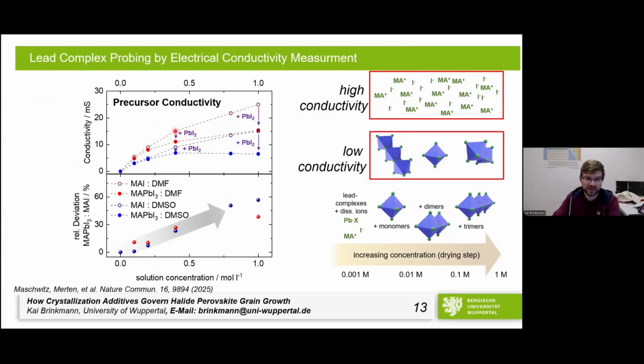So the methylammonium iodide, these are the empty signals here. This is a dissociated salt. So here, this is basically how we would expect the conductivity to go if we have a well dissociated salt, with no bundling together of the colloids. And then when we add lead iodide, so basically when we go from a salt solution into a perovskite precursor, we drop in conductivity, which means that we add material that should create more ions, but instead it drops the conductivity. It means we go from this case to this case. So we can confirm once again, we have larger things in the precursor that conduct ionic charges less well. So everything so far points to the fact that when we increase the concentration, we have this buildup of colloids, and we were very happy about this because now we are good to probe how we could use this to increase the grain size and to explain why the grain size goes up.